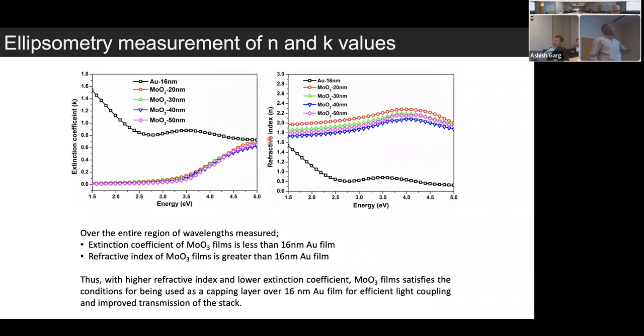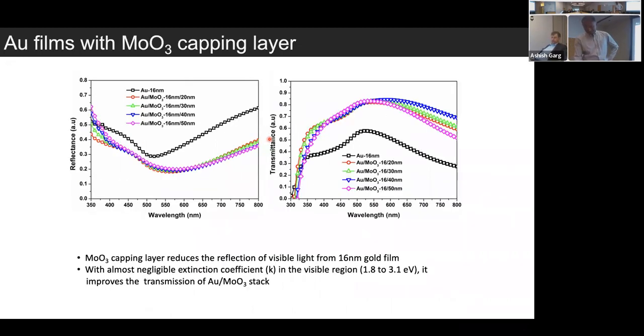So we did optical ellipsometry to understand n and k values, and what we found is that the extinction coefficient of the moly oxide film is lower than the gold film, and the refractive index is greater, which is a good thing because then you can absorb more light into the active layer by transmitting. It basically improves the light coupling in the device.